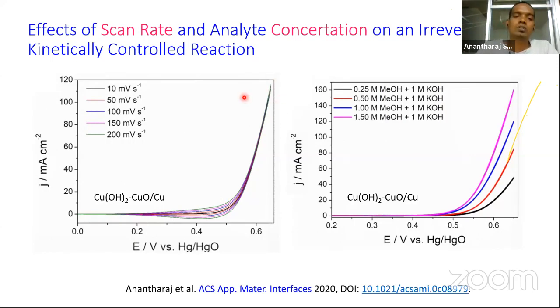That can be oxygen evolution, hydrogen evolution, or nitrogen that is evolved from ammonia oxidation or hydrazine oxidation or urea oxidation. So this could be any gas evolution reaction. This will be the response when you increase the scan rate, which means that the kinetic current is independent of scan rate. Okay, so one interesting thing that you can notice here is the self oxidation and reduction peak of copper hydroxide to copper oxide hydroxide and copper oxide to copper oxide hydroxide, which is controlled by diffusion. That's why we witness an increase in current density with increasing scan rate.